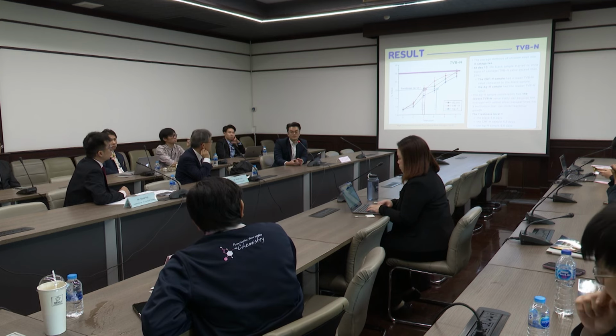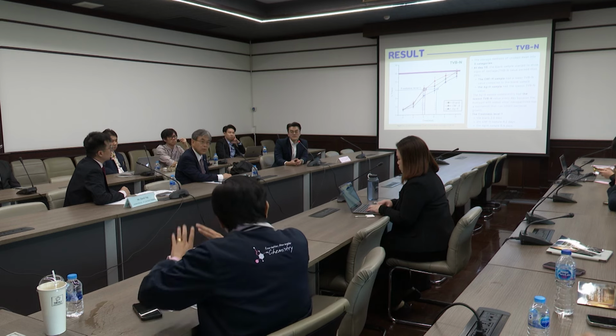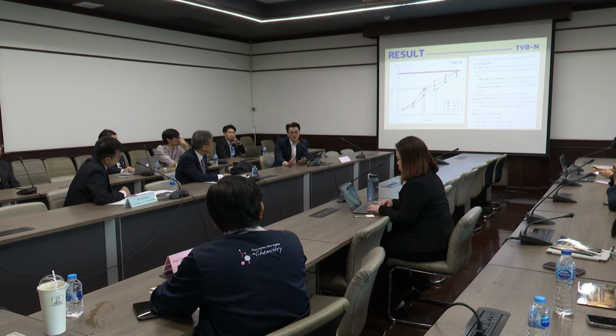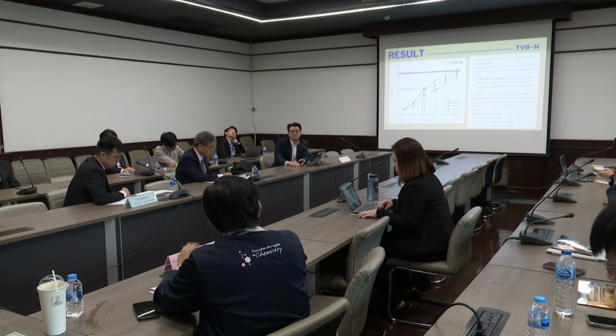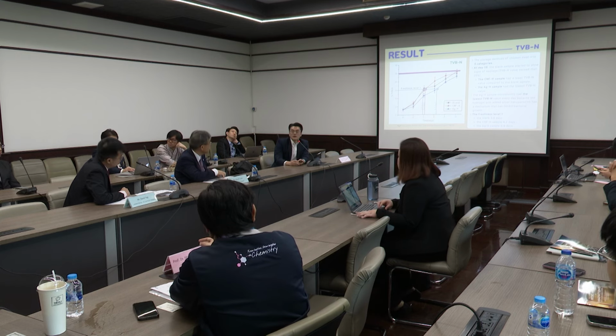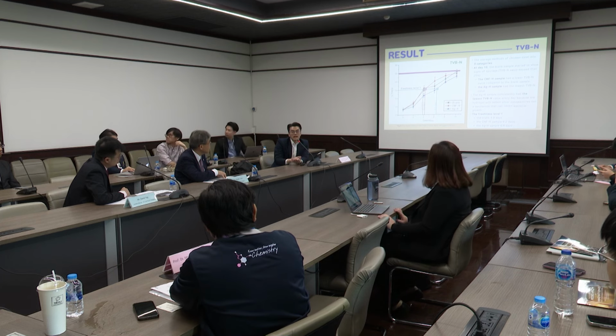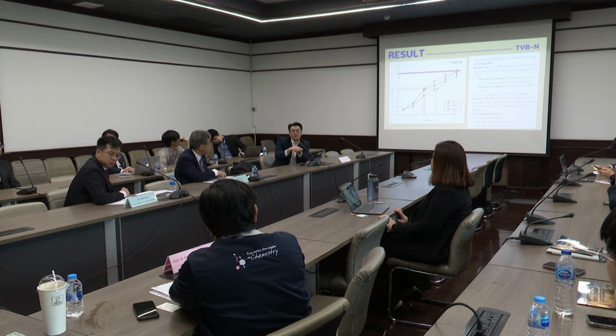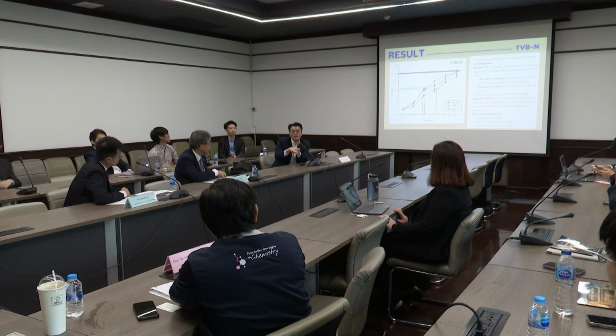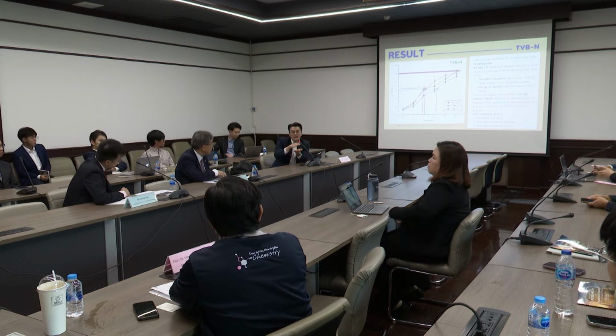That also leads to my second question. How did you test with the meat? Did you wrap it all over or just put it underneath? We just put it under the meat. We used meat of approximately 100 gram with a hydrogel diameter of 8.5 centimeter and 2 millimeter thickness. So it's not covering the whole meat. Yes. But normally when you do packaging, you cover the meat, right? So it may work. We aim to use it as an exudate pad to replace the absorber pad used nowadays, because the absorber pad nowadays doesn't have any antimicrobial property, so we aim to replace that.